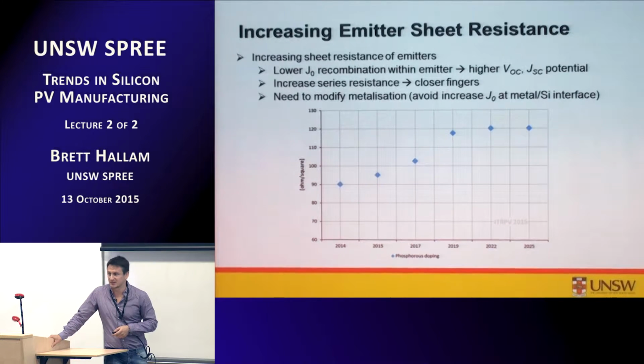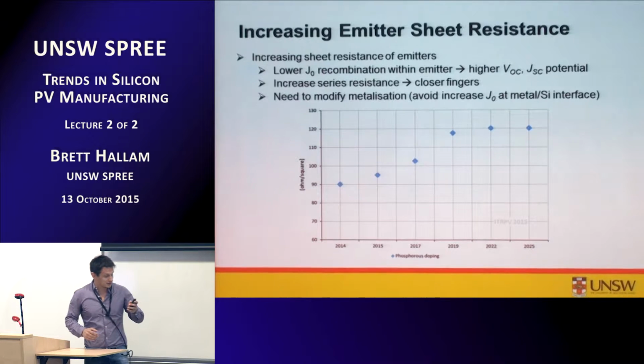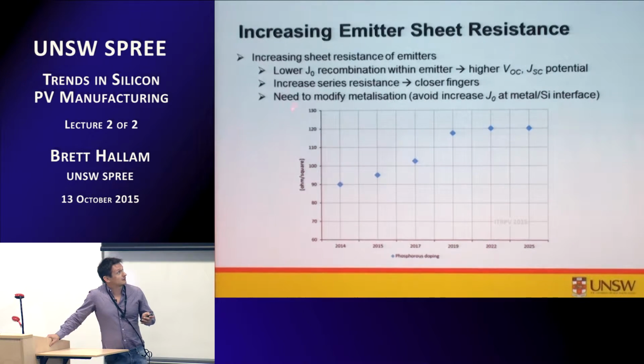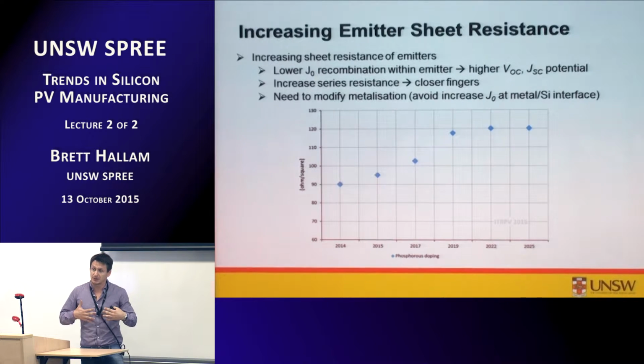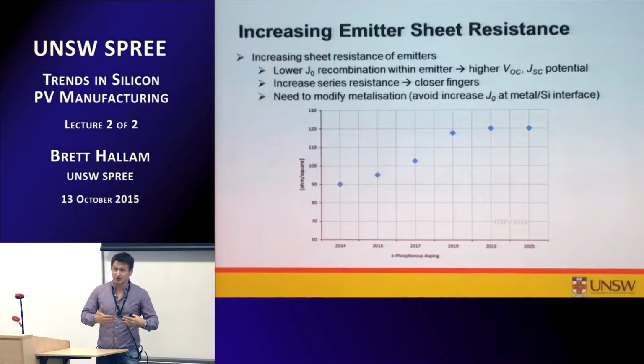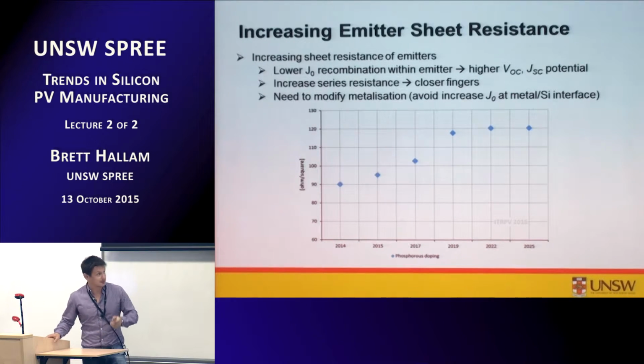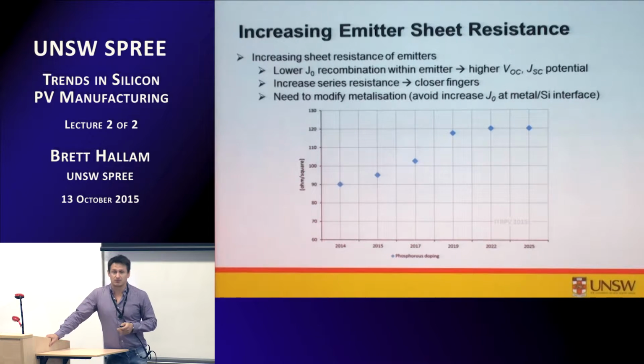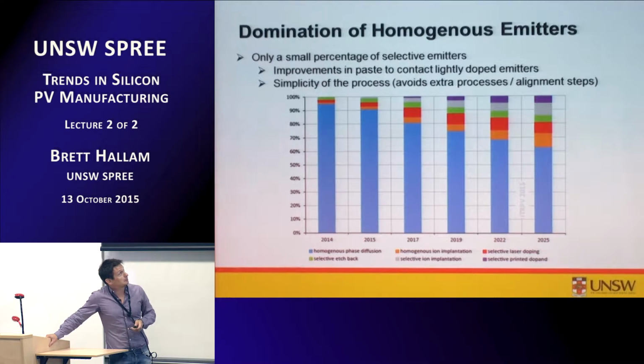Yeah, yes, and that's typically what is happening in the industry. People are looking at thinner dimensions, trying to increase the aspect ratio of the contacts, etc. And yeah, so we need to increase or modify the metallisation process. Also from a J0 point of view, typically as we go to these higher sheet resistances, we might bring down the peak doping concentration. So that increases the minority carrier concentration, not good for recombination at the metal silicon interface. So a lot of the development, like Bram mentioned before, has really come from the screen printed paste manufacturers, as well as from the screen printer tool manufacturers. And that's where a lot of these developments are coming from.